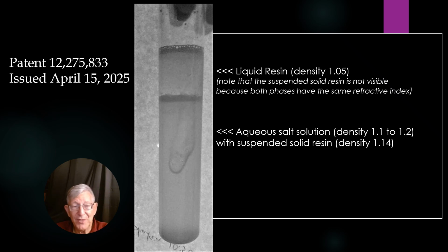And it accomplishes two things here. One, not only have you separated this material, but you've separated it without creating gravitational forces, and you have not created viscosity forces. If you create a material in the middle of a pool of liquid resin, and then you try to take that solid material out, what you find is that if it's not a massive type of material, if it's got some very fine structure, if you try to pull it out, the viscosity of the liquid resin is going to cause viscosity drag, which is going to cause the bending and deformation of whatever it is you're trying to manufacture.